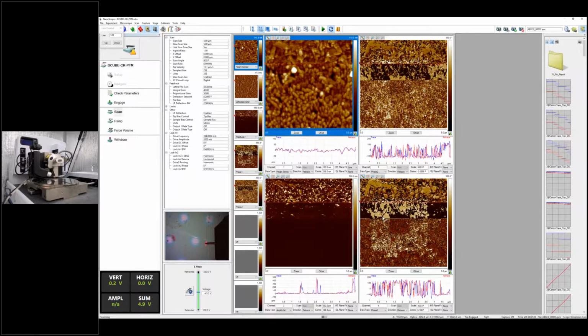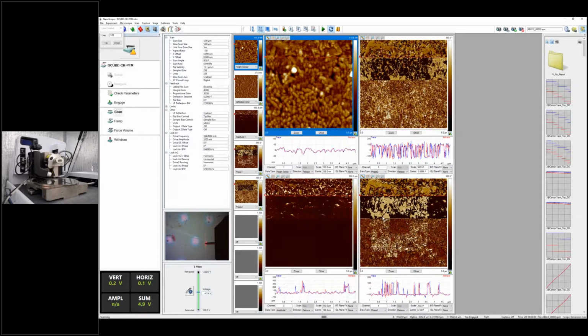But I also mentioned earlier in the presentation, this contact resonance can shift during scanning. If you do a single spot, maybe it's okay. But if you are trying to scan an image while doing this kind of PFM measurement, then depending on the contact, this frequency can be different. So in order to address this problem, we introduce DataCube contact resonance PFM, which can actually track the contact resonance at each pixel. So what we need to do is first determine in what kind of range this frequency may change. So here I'm just doing a quick sweep of the frequency.